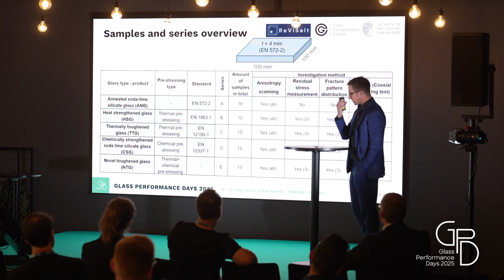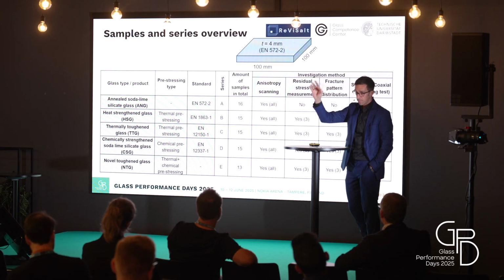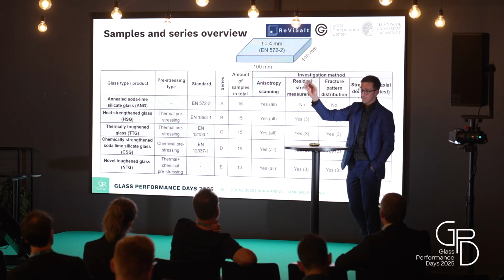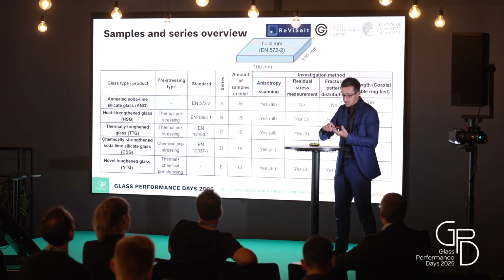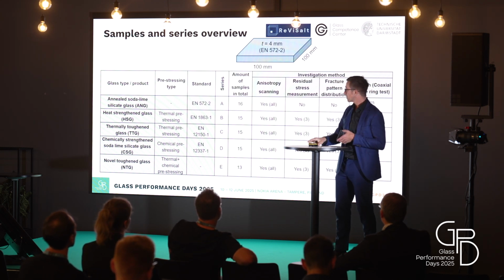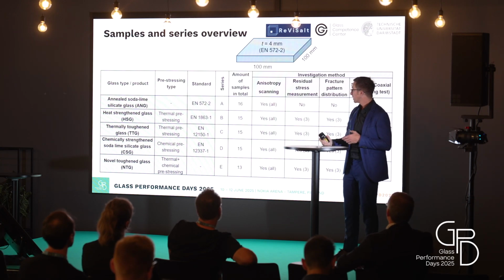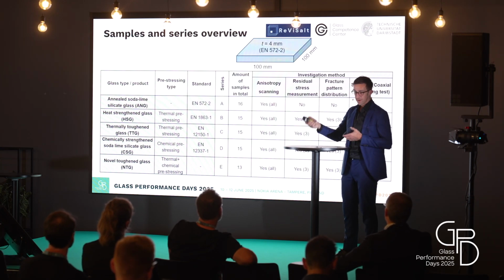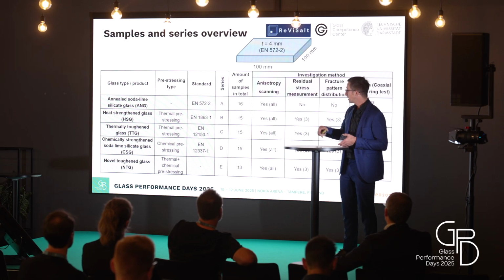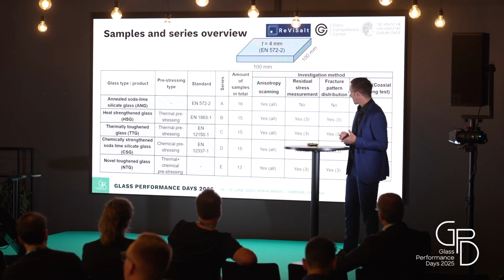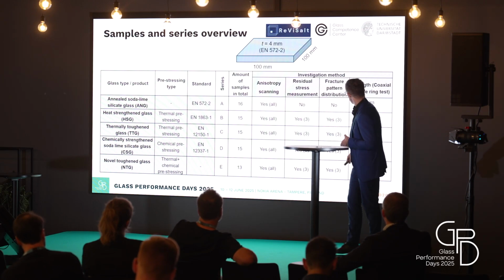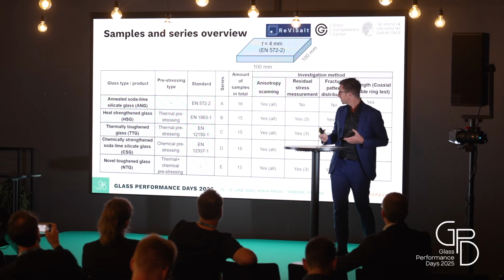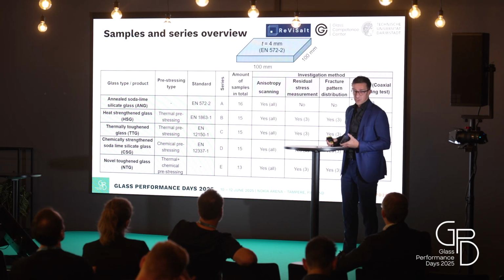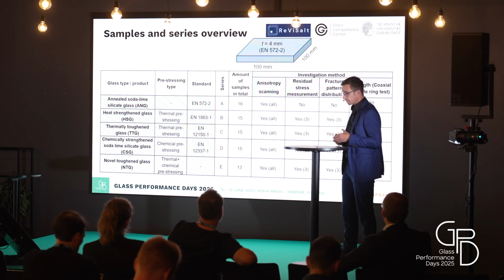Now I come to some results. We conducted some tests. We bought glass, one batch, 100 by 100 millimeter, and did the cutting, grinding, and so on. Then we produced 4 millimeter thickness. We had normal annealed soda lime glass, then we used this to make heat strengthened glass with a company. Then thermal toughened glass, the fully tempered glass, then chemical strengthened soda lime glass, and then also the novel toughened glass. Here you can see the standards, and we conducted different tests: anisotropy test, residual stress measurements, fracture distribution test, and also the strengths. This is also very important.